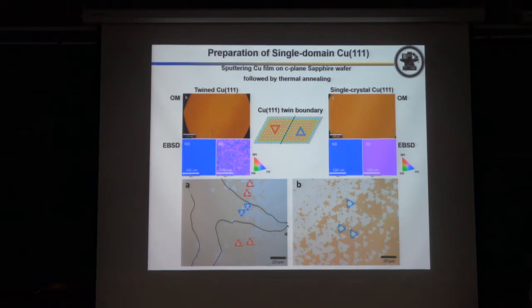But typically, you cannot deposit single crystal copper. So you have to find some way to improve the crystallinity and eventually achieve single crystal. So we use thermal annealing. That's quite simple. You put it in a furnace, change the temperature, and find good annealing conditions like temperature, and also gas flow like hydrogen, argon, and so on. So you can improve the crystallinity and become single crystal. As you can see, this has some grain boundaries, and the grain orientation is not the same. But in this case, they have only one direction. So the key is the substrate, not the growth.